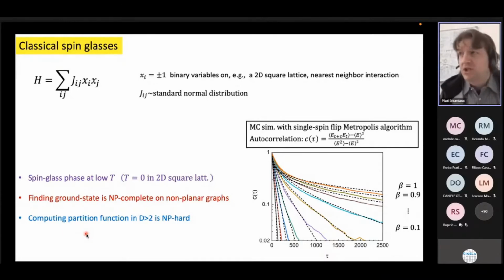So in general, it is known that simulating spin glasses at low temperature and simulating their thermodynamic equilibrium is a challenging computational task. And here on the right, you have a plot of the energy autocorrelation function that you would obtain if you use the standard Metropolis algorithm to simulate the thermodynamic equilibrium properties at different temperatures. And notice the semi-log scale. So at high temperature, when the inverse temperature beta is small, your standard single spin flip Metropolis algorithm gives you a very efficient simulation. But if you decrease the temperature, at some point you see a freezing, and at some point the simulation is pathologically inefficient.